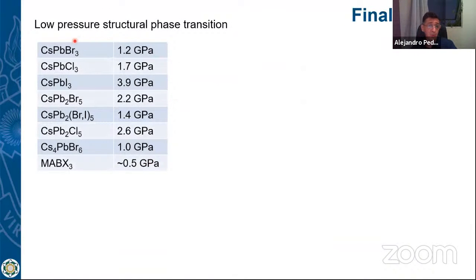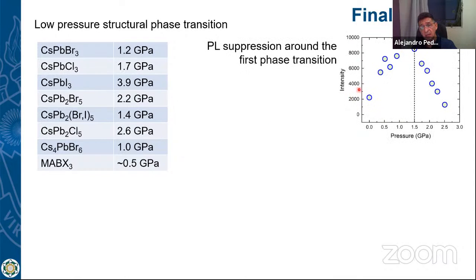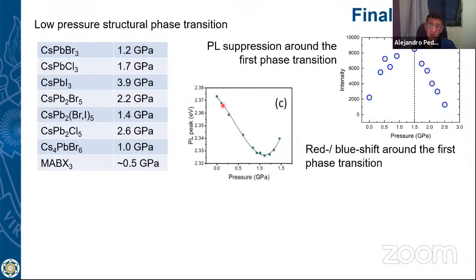As final remarks, we can see that in these materials it is very common to see low pressure structural phase transitions. It is also very common to see a change in the luminescence, which is suppressed a little bit above the first structural phase transition, but not at another structural phase transition. There is a red shift followed by a blue shift in these compounds, and this change happens not exactly, but around the phase transition.